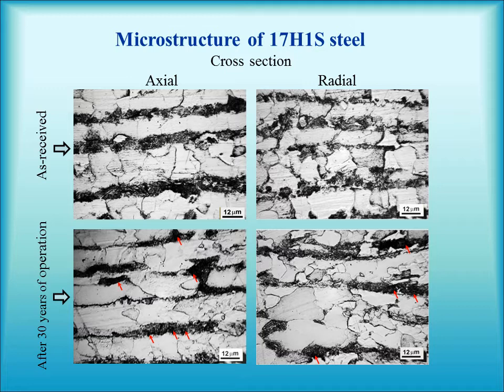Considering operated steels, we should take into account influence of hydrogen, which usually occurs during long-term operation of gas pipelines. Hydrogen is accumulated mainly at the boundaries ferrite-perlite, whereas perlite itself serves as a barrier for it due to its lower permeability for hydrogen. However, hydrogen can penetrate through ferritic lamella into perlite. To a certain distance, it causes embrittlement of the boundaries ferrite-cementite within perlite, and in this way facilitates a spalling of cementite constituent.